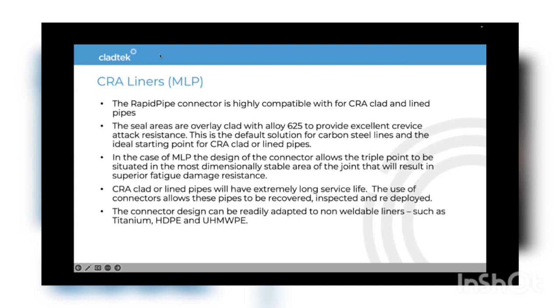Because CRA clad or lined pipes are designed for life of field, we expect at the end of the service life, providing the anodes and external coating have done their job, that the pipe will be more or less like new at the end of its life. So again, CRA particularly lends itself to being reused, if this technology can be used on carbon steel pipes. We think that the hurdles to compete with welding are more significant comparing carbon steel. But once you jump to CRA, because the welding productivity of CRA is typically around 1/3 of carbon steel, then connectors really come into their own.